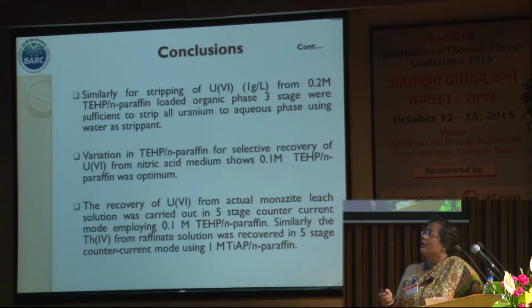Similarly, for stripping of uranium 6 from the 0.2 M TEHP/n-paraffin loaded organic, 3 stages were sufficient to strip all the uranium to the aqueous phase using water as stripant. I forgot to say that water was used as the stripant in this case.